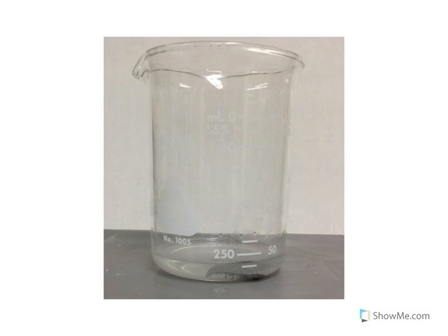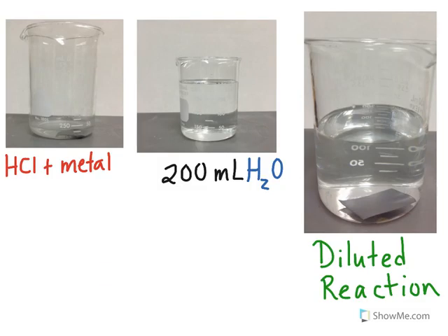Place the metal piece in a 400 milliliter beaker and add enough 6 molar hydrochloric acid to cover the metal. About 25 milliliters of acid should be plenty. Let the beaker stand until the rapid bubbling stops. When the signs of reaction indicate that all of the zinc has reacted, add about 200 milliliters of tap water to the reaction beaker. This will dilute the hydrochloric acid solution and stop the reaction.